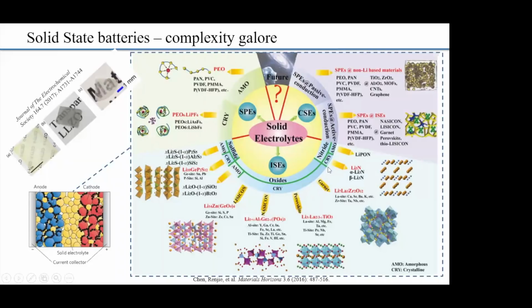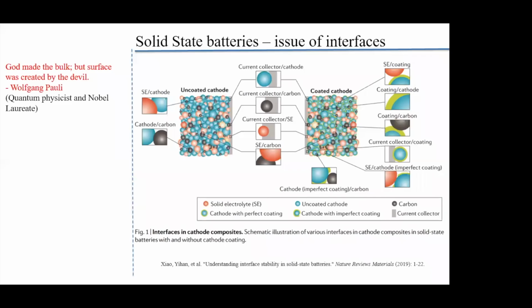And then there's the issue that some of these oxides are pretty stiff and brittle, right? If it is very brittle, then how are you going to make a cylindrical cell? Or maybe you just need to make a flat pouch cell and make sure there is no inadvertent pressure on these kinds of batteries. Basically, if the battery is a little bit compliant mechanically, that's good because it gives it toughness. But if it is too brittle, that can become a failure point on its own, because one brittle fracture can lead to an isolated region, which could lead to all kinds of problems.